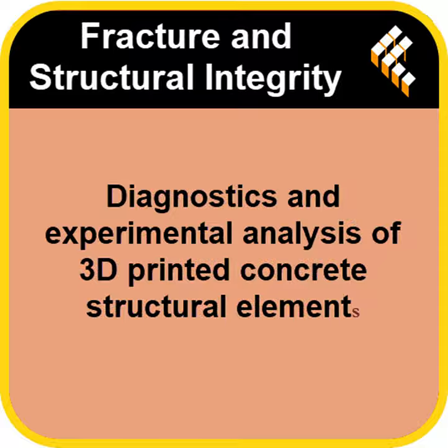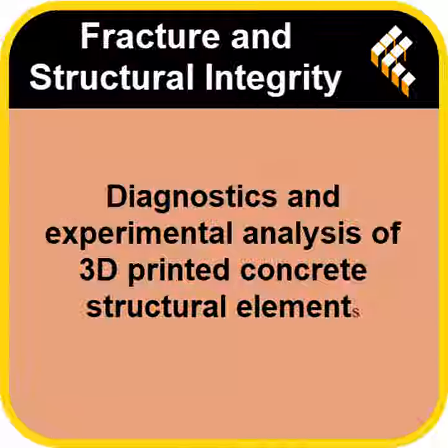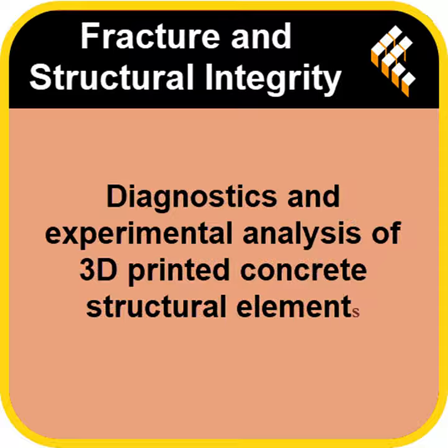Because that sabotage, as you call it, gives us crucial insight into real-world performance. Look, if this technology is going to be used on a real construction site, you have to know how it handles a small interruption or a slight change in the concrete flow. So it's about reality, not perfection. Exactly. So 4 columns were the clean reference ones. Yeah. But 2 of them, CP1804 and 05, had these built-in defects. What kind of defects are we talking about? So CP1804 had a section about a third of its length where the printed filament was just narrower. It simulates a brief interruption in the flow. Okay. And CP1805 had a very similar issue, just a reduced filament width on one of its long sides, things that could easily happen on site.